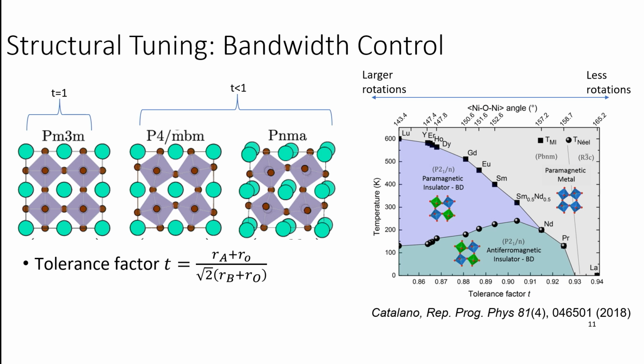And as you can see, you can go from lanthanum, which has the smallest rotation because lanthanum is the biggest ion in that series. Lanthanum nickelate is a paramagnetic metal. And as you decrease the size of the rare earth ion you have in the system, these octahedral rotations increase, and the system goes into this anti-ferromagnetic insulating phase.